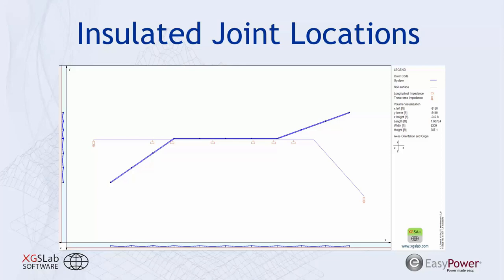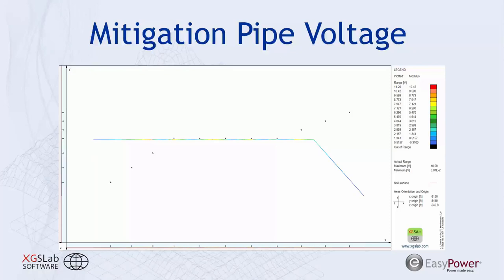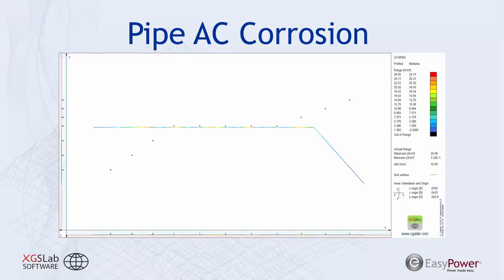When you're really incorporating this type of mitigation, you may have additional concerns during the faulted state, because during that faulted state, you can have significant induction again for a short period of time, but that is a significant induction and significant voltage that can break the dielectric strength of this insulated joint intended to protect you from AC interference, and it's really causing a new issue to resolve. So when you incorporate those breaks or those insulated joints in the pipeline, you're reducing the length of exposure for the pipe. And by doing that, we're able to reduce the voltage to less than 12 volts that's induced upon this pipe section. And that reduces our AC corrosion, or our amps per meter squared again, to acceptable limits below that 30 amp per meter squared value.